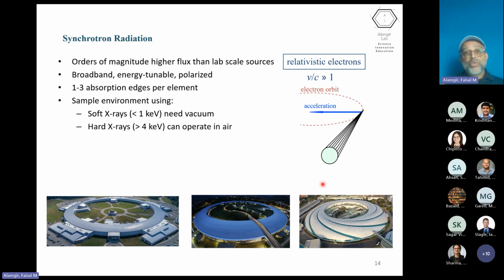And so the ability to move in energy and select the energy at which you trigger that emission process makes X-ray emission much more attractive if you have a broad X-ray source. So the broad energy X-ray source, where the intensity of the X-rays is also high and fairly flat across that energy range, is a requirement, or it has been historically a requirement for these type of techniques. And so these kinds of techniques have resorted to these large facilities that generate X-rays by phenomena that are difficult to replicate at a lab scale.